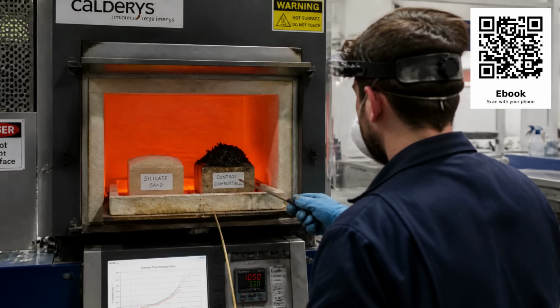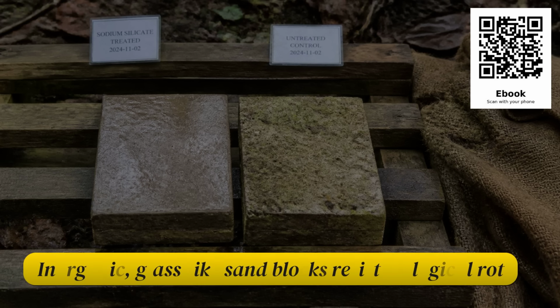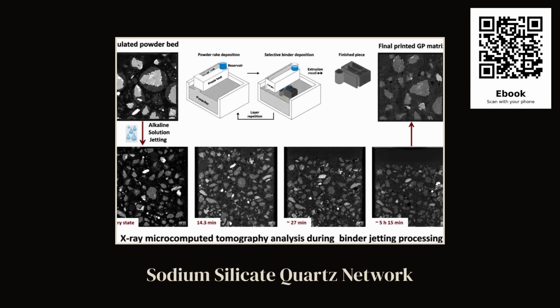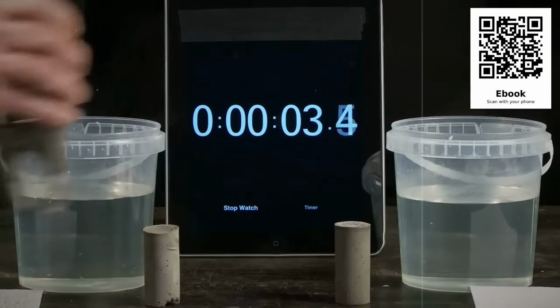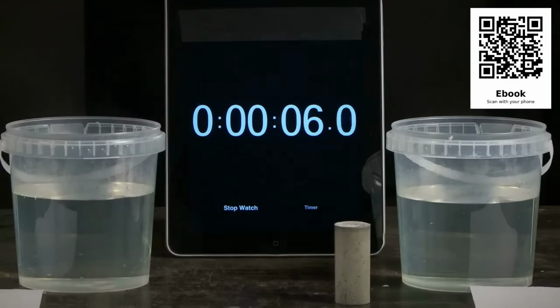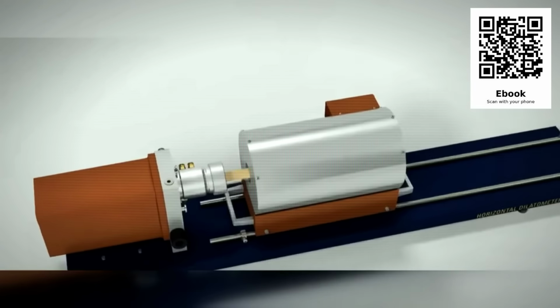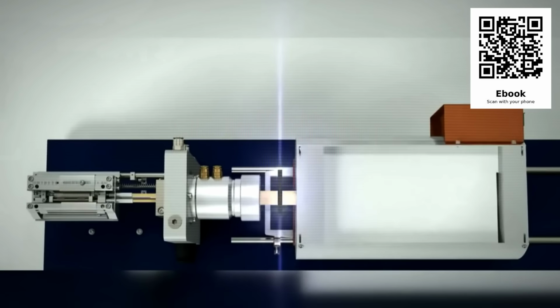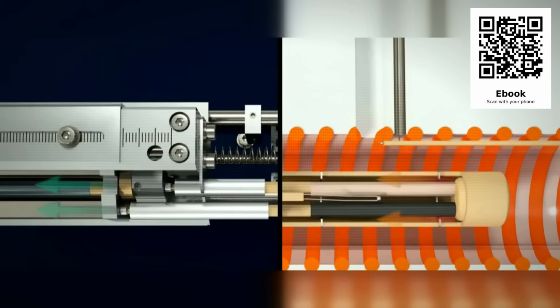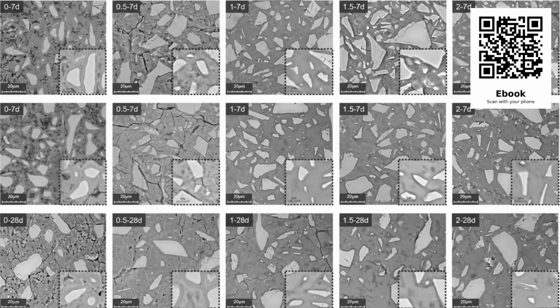This is why silicate-bonded sand has the properties it does. It does not burn because there is nothing in it to oxidize. It does not rot because it is not organic. It does not freeze and split easily because the porosity is small enough that water in the pores can expand into adjacent void space without generating destructive pressure. It resists most acids because silica itself is acid resistant. It is dimensionally stable across a wide temperature range, expanding and contracting less than Portland cement when heated and cooled. And it gets stronger over time, not weaker, because the silica network continues to densify and cross-link for years after the initial set.